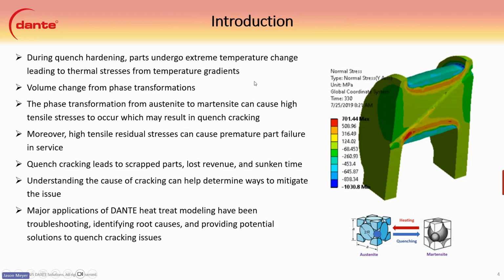A little introduction here to quench hardening. During quench hardening, parts undergo extreme temperature change, leading to thermal stresses from temperature gradients. There's a volume change from phase transformations that occurs when you transform to austenite and then to martensite, back and forth, or even to diffusive phases. The phase transformation from austenite to martensite, which you can see in the little figure at the bottom right here, causes high tensile stress to occur, which may result in quench cracking. It's basically from the density change, from the more dense austenite transforming to a less dense martensite that takes up larger volume.